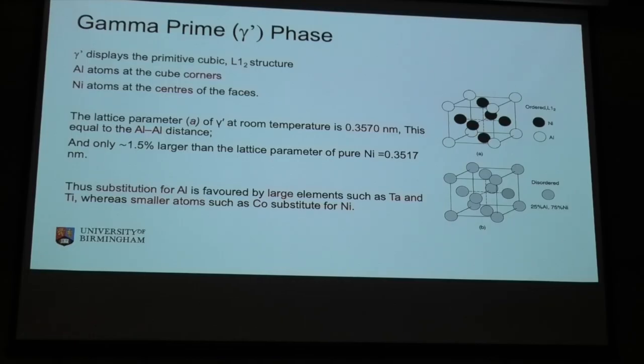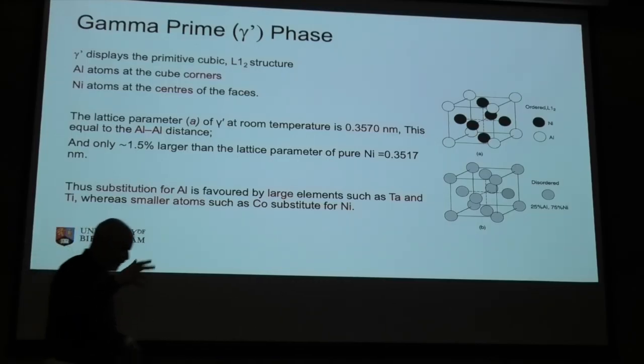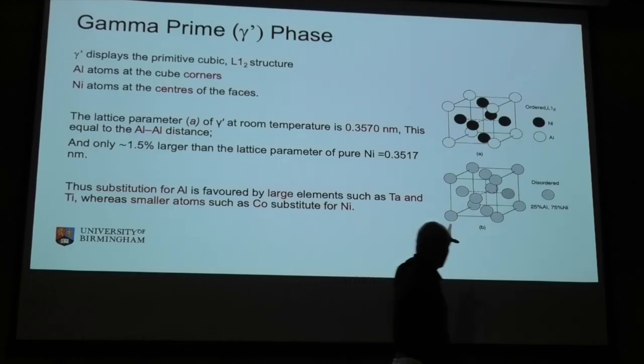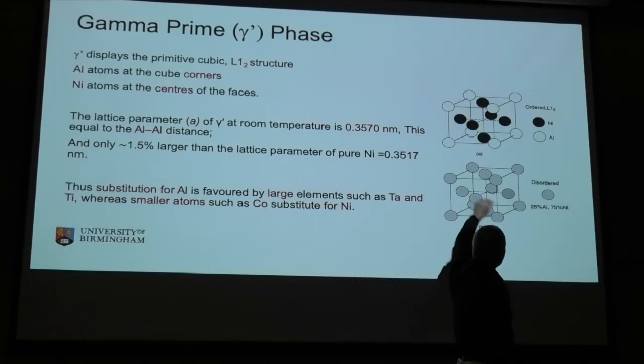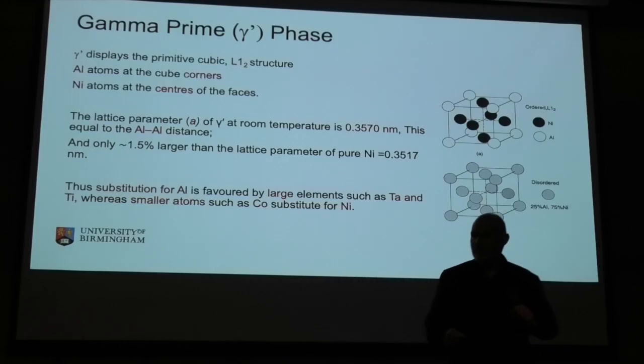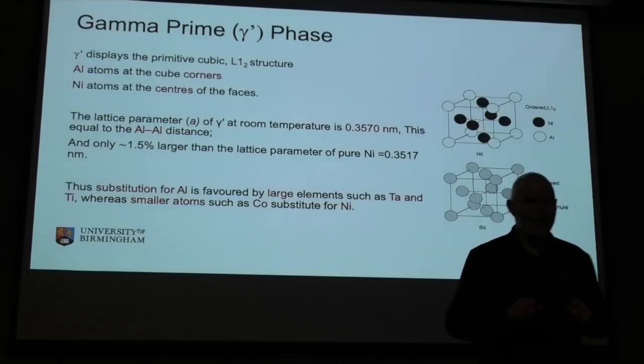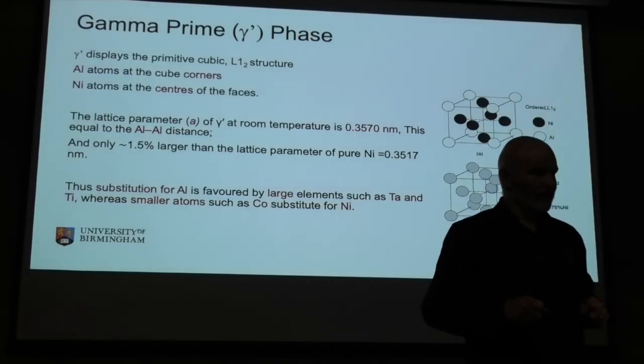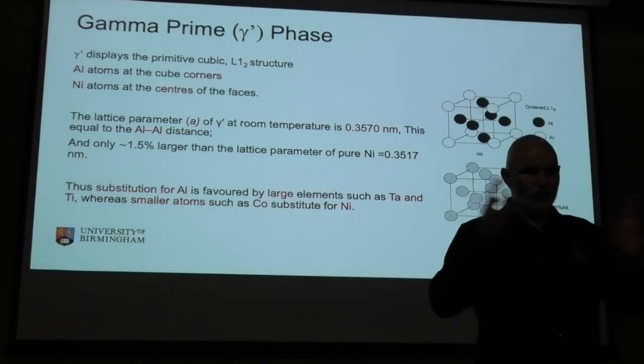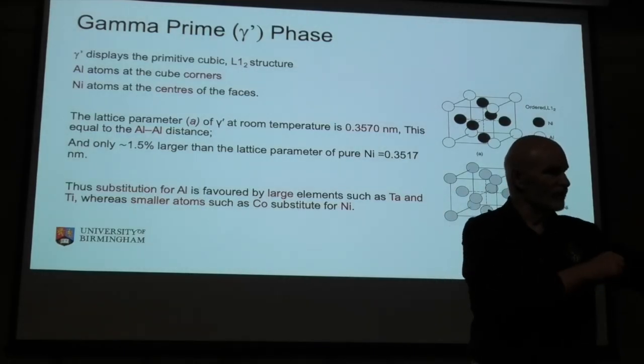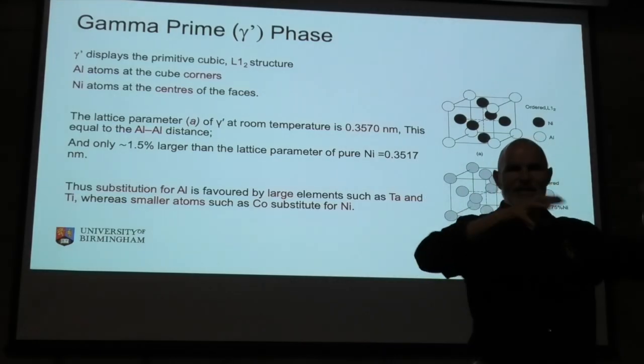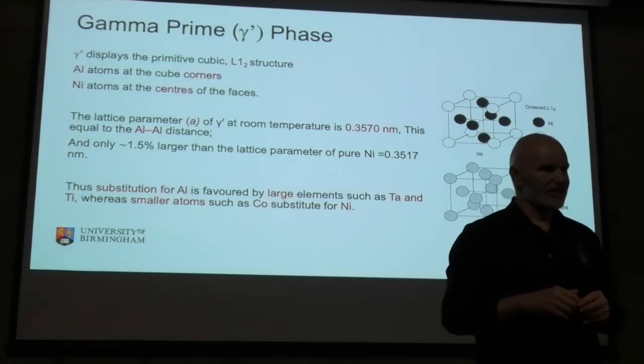So that's the technical stuff. What happens is we've got face centred cubic, a particular cubic crystal structure, really good for strength. But then they get fussy - the nickels sit on the face cubes, the aluminiums sit on the corners because they don't like sitting next to each other, so they all disperse to their corners. As soon as you get to the right concentration of aluminium, it splits up, sits in its different places, giving us this coherent precipitate.